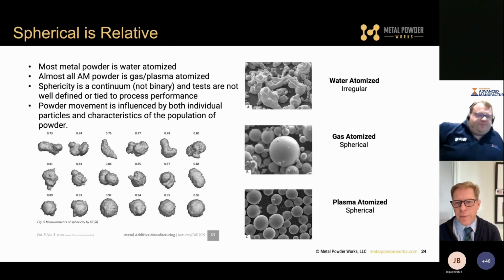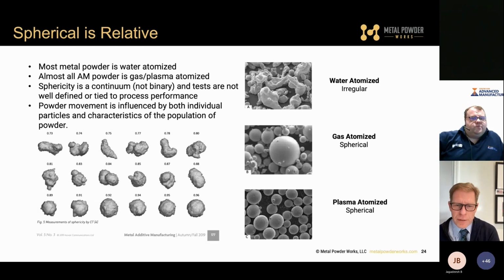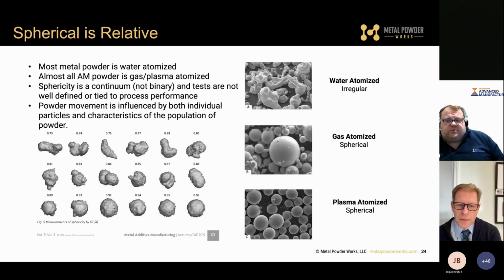And so quite simply, if you think about natural packing factor as opposed to tap density, none of these systems have truly a tapped density situation. We're not tapping any of these things 100 or 1,000 times to get perfect density out of it. Natural packing factor is I throw powder down onto a table or into a jar and it naturally packs. Ellipsoids naturally pack very well. They pack as good as spheres do after several taps. So just ideas, again, for you to think about.